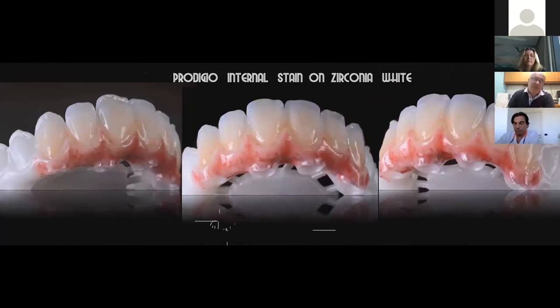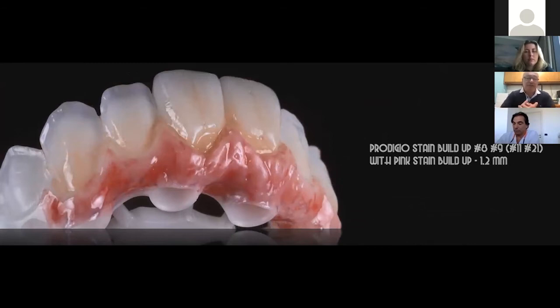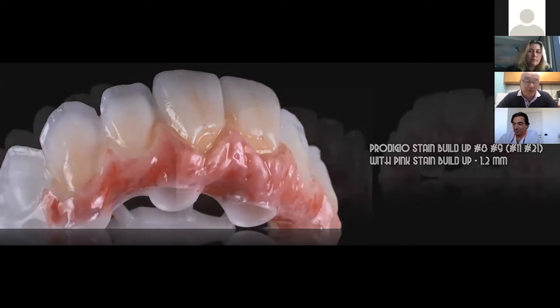This material has been created also to create a good bonding between zirconia and porcelain. You can use it as a stain, as an internal stain, or as a bonding material. Let's say you want to build the porcelain on the buccal of this zirconia: you can use those stains to characterize the color, but at the same time you start to create the initial chemical bonding between the feldspathic porcelain and the zirconia as well. That is one of the most important things. In this situation, you can see you can build up to 1.2 millimeters only with a stain.